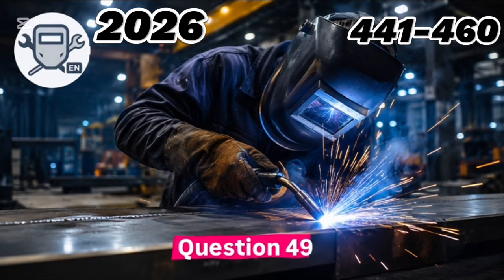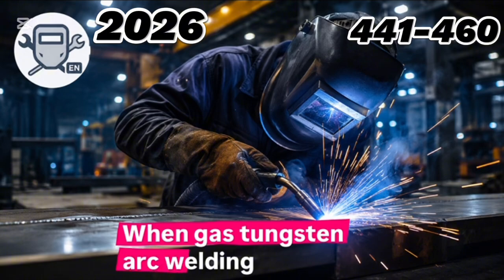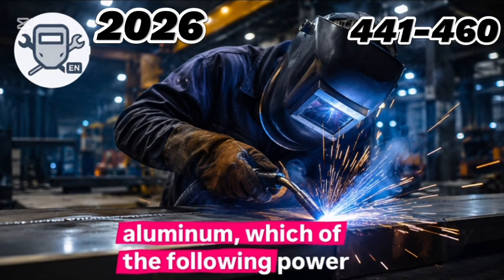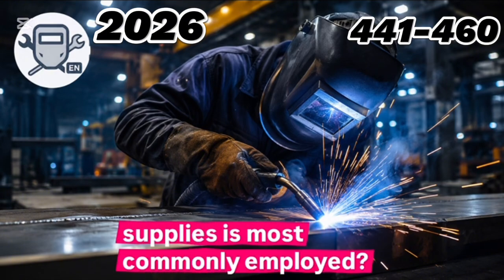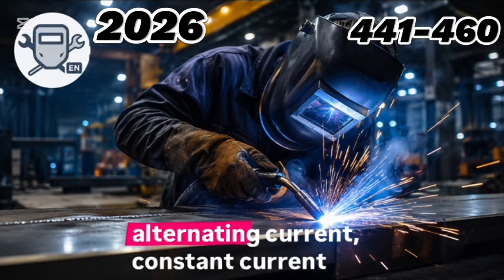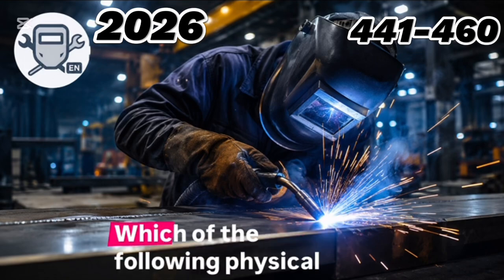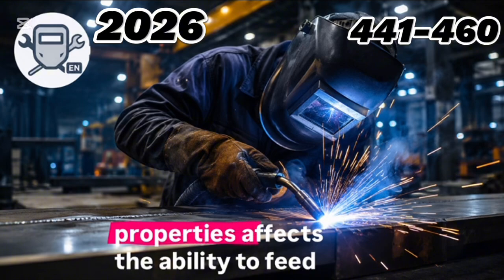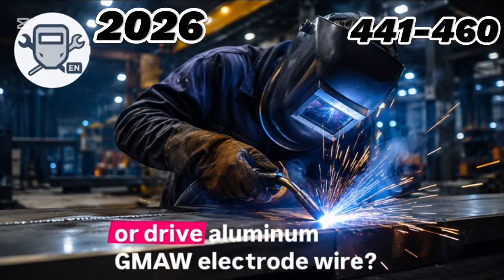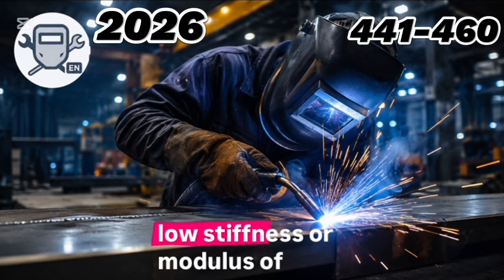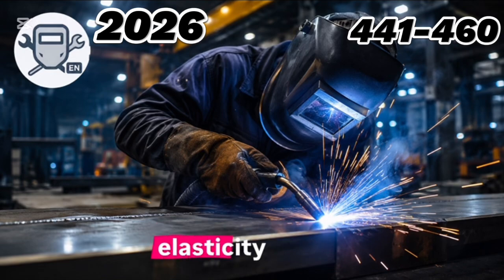Question 49. When gas tungsten arc welding aluminum, which of the following power supplies is most commonly employed? Answer: alternating current, constant current. Question 50. Which of the following physical properties affects the ability to feed or drive aluminum GMAW electrode wire? Answer: low stiffness or modulus of elasticity.